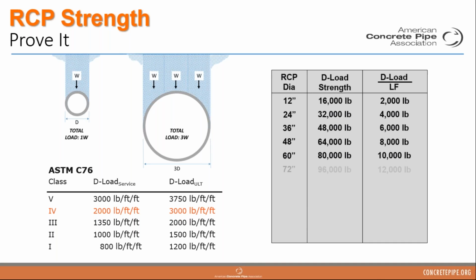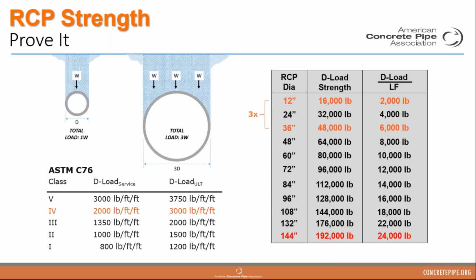This chart is an example of Class IV reinforced concrete pipe. So that's a D-service load of 2,000 pounds per foot per foot, and a D-ultimate of 3,000 pounds per foot per foot. Looking at that service load of 2,000, if we look at the 12-inch pipe and compare it to the 36-inch pipe, the strength of that pipe increases by three times. So 16,000 pounds is one-third as strong as 48,000 pounds. And that's true all the way down through this chart. If we take the 12-inch pipe and compare it to a 12-foot diameter pipe, that 144-inch pipe at 192,000 pounds of strength is 12 times stronger than the 12-inch pipe.